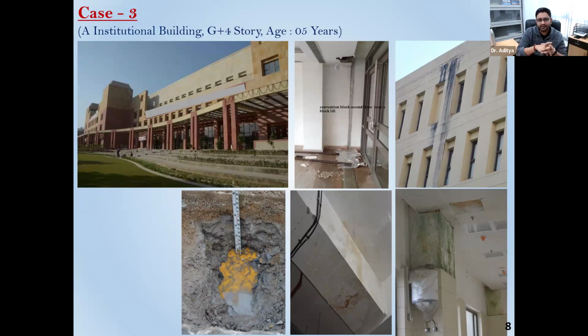The water during the rainy seasons used to percolate through the PCC that was laid above the insulating puff, and it was basically being stored in this insulation, because it's a puff of 6 inches. So it acts like a reservoir which can hold a good amount of water. And then this water used to slowly seep through all the downward sloping areas, be it a joint or the periphery, wherever it was finding its way, it would go there and keep on seeping at a very slow rate, and therefore you will find the seepage throughout the year in areas where it is not supposed to be, because there is no plumbing as such.